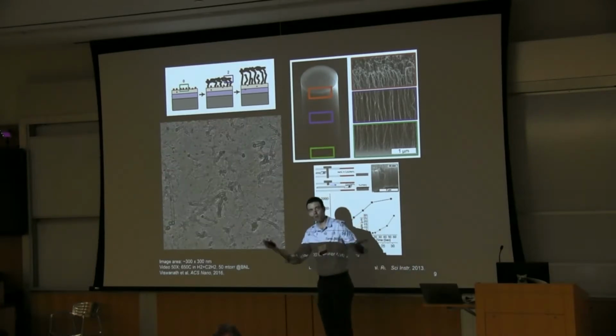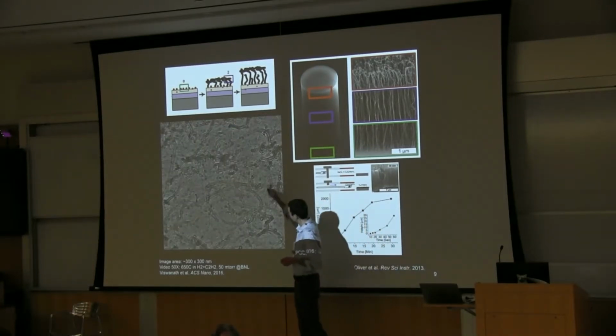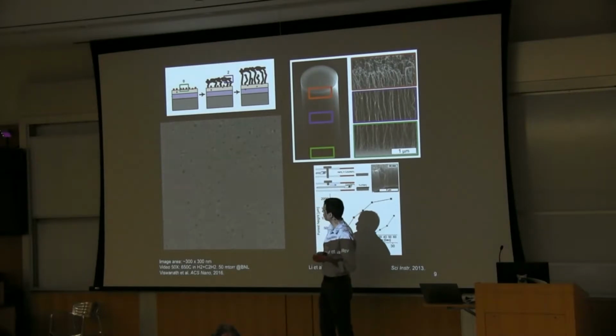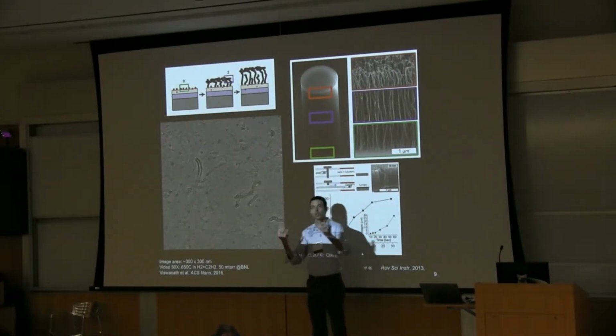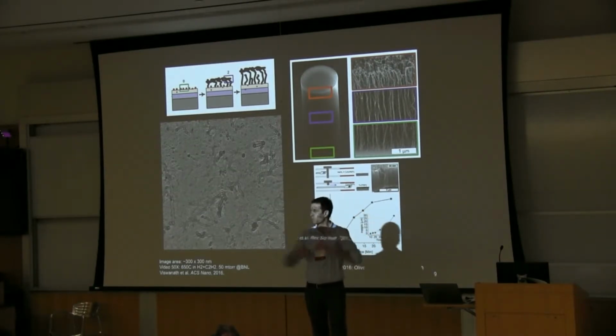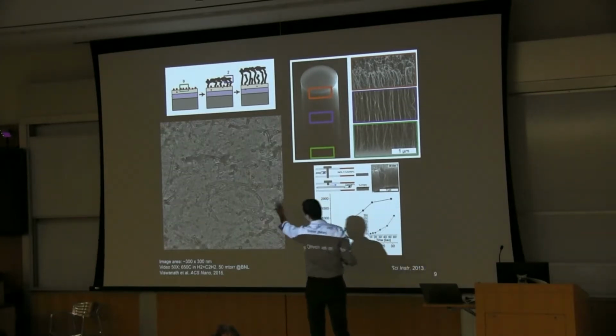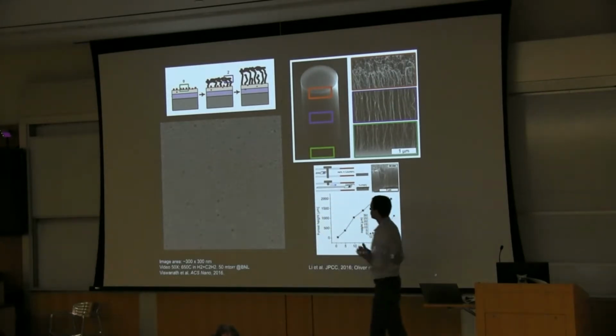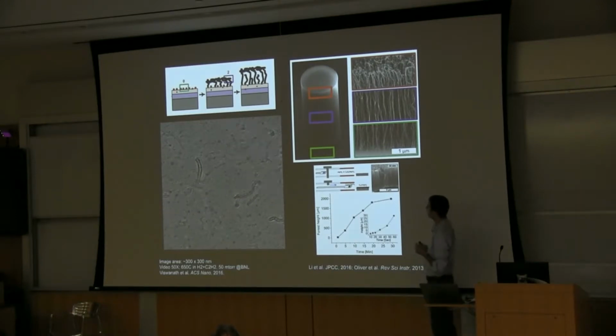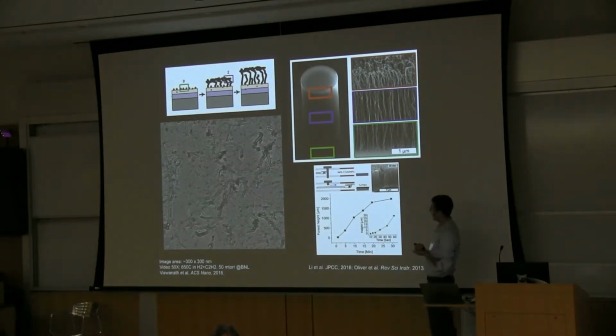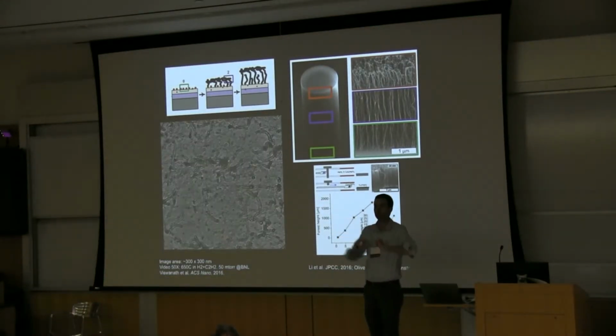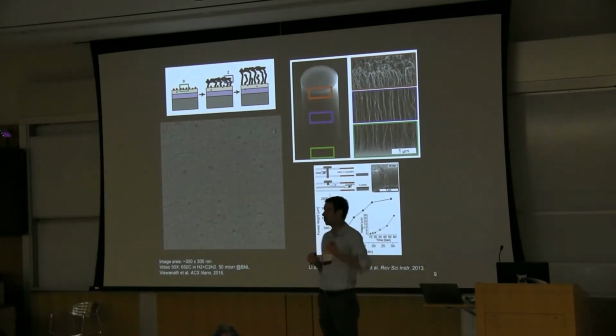So you put a thin film of metal on a silicon wafer, it breaks up into nanoparticles, and you introduce a hydrocarbon, and the nanotubes will start nucleating individually and then self-assemble into this vertical structure. This is a really fascinating example of competition between mechanics and chemistry, but in practice what this let us do is get a better understanding of how to make these nanotube forests or microstructures in our lab, patterning catalysts by